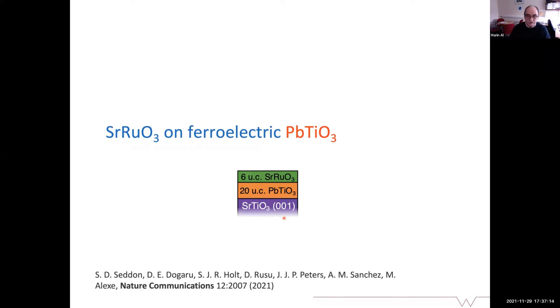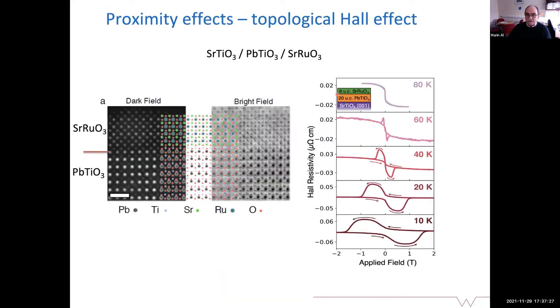So we grew lead titanate on strontium titanate, and then a few unit cells, you see here 6 to 8 unit cells, of strontium ruthenate on top of that. And the idea was, okay, we do have this topological Hall effect. We characterized that we have a massive topological Hall effect, much higher than the normal. We've looked also into the structure, and the structure was absolutely great.